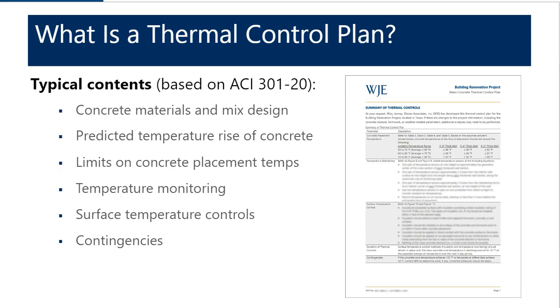And then it will also include contingencies. What should you do in the event that you either exceed your maximum temperature or exceed your maximum temperature differential? Or in better practice, what happens if you come close to exceeding those so that you can take steps proactively to avoid exceeding those limits in your actual placement?